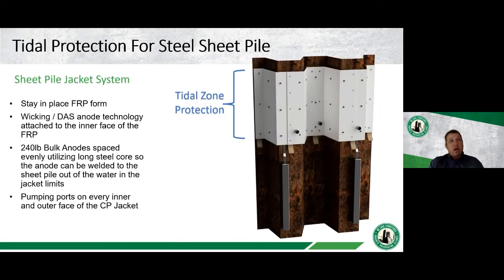So the next thing I had mentioned was the tidal protection for steel sheet pile walls or bulkhead walls. We've been working on a number of other things with this as well. Again, this is a very difficult zone, that tidal zone. It's a really, really difficult place to protect, especially when your coating's damaged. You can put bulk anodes, as you can see here in the picture on the right, and a bulk anode can easily protect everything in that water column. It's a very, very easy fix, but it's that tidal zone.